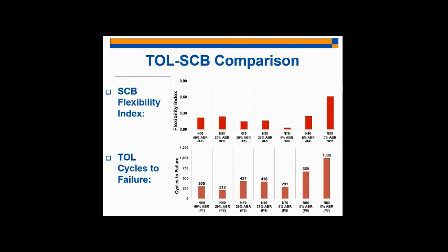And what we saw here basically is that there's pretty decent correlation between the SCB flexibility index values and the TOL cycles to failure. If I look at the SCB flexibility index values, the highest performing mixtures are, this is kind of cut off here, but the x-axis is the same. The best performing mixture is basically P7, and one of the lowest performing mixtures is P5.